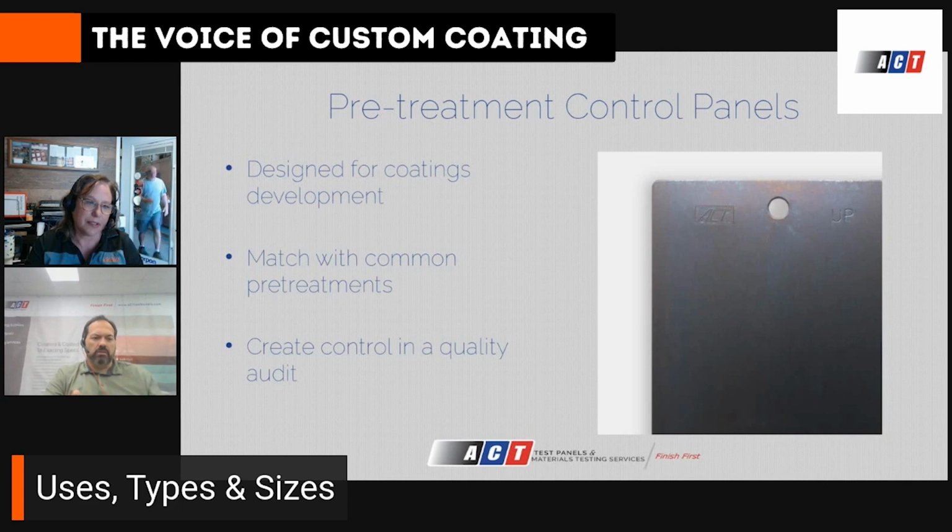The architectural markets are a little bit more particular about that, but typically not on powder coating. So the extrusion side of that isn't as much. There are some liquid coatings that come out of coil lines that actually fold back on themselves. They call it a 0T. So there's nothing in there. You can fold the metal however thin it is right back on itself. And that's extreme. Powders tend to be a little bit too rigid for that. They're not necessarily designed for it, both for the mil thicknesses that you use, because a powder system is going to be 2 mils plus. Those systems are typically less than one mil thick.